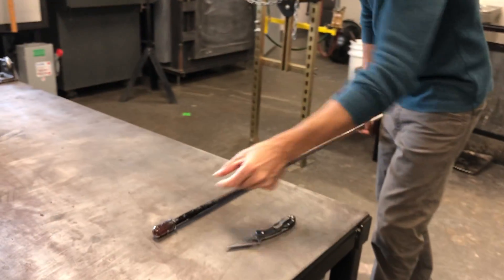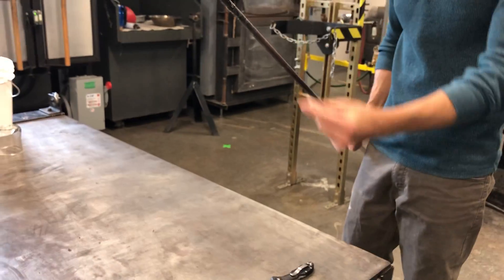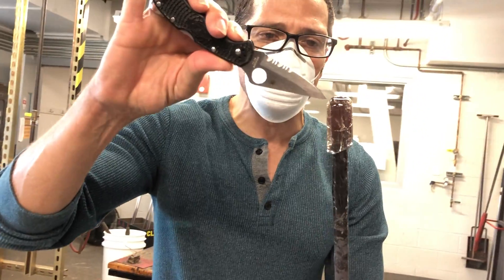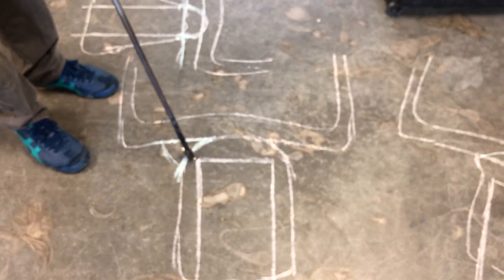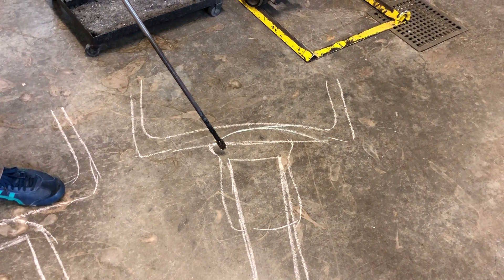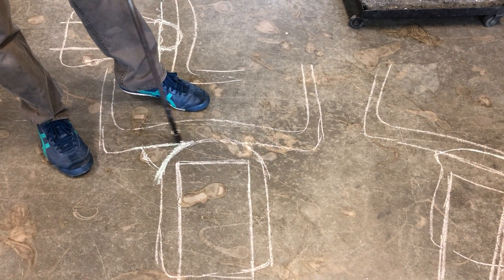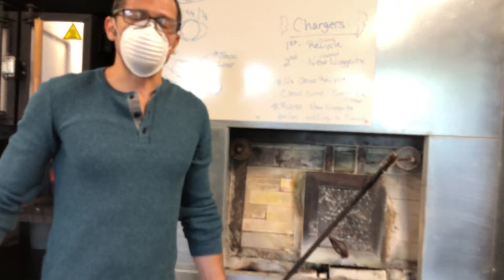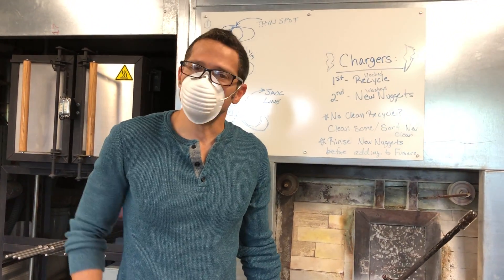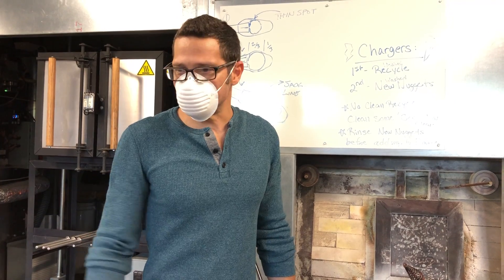When I'm marvering, I'm trying to make this a thin skin so my left hand's on top. I'm not just blindly pushing forward though, because I don't want to peel all the glass off the tip — I need support right here. See on my drawing? I need support here. No support breaks off and sticks on the bottom of my piece. Way too much support — big blobby thing, no curve. This support and a nice curve going into the bottom of the piece takes you 30 seconds to make, and you'll have a lot more success and happiness not having to go into the cold shop to fix a problem that shouldn't exist from making a simple puntee.